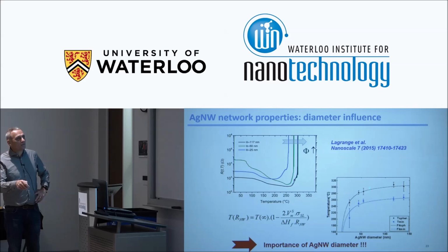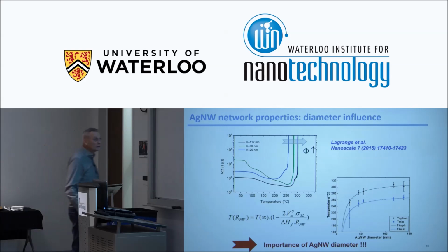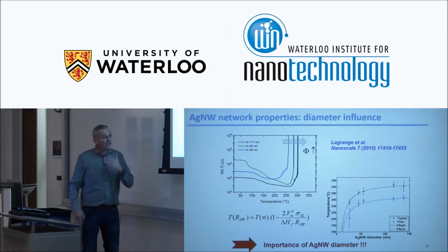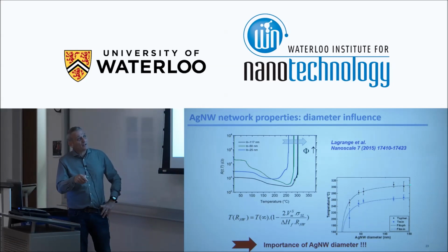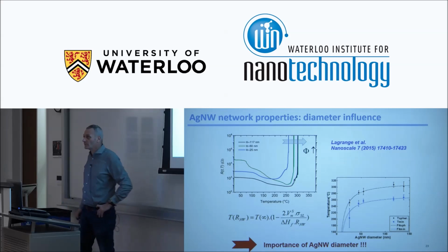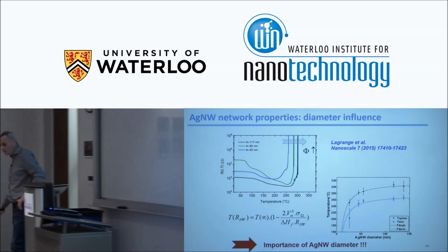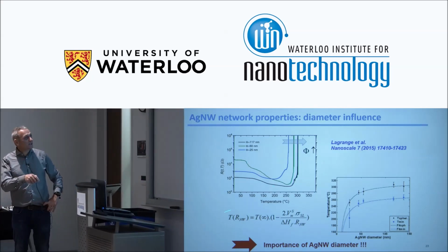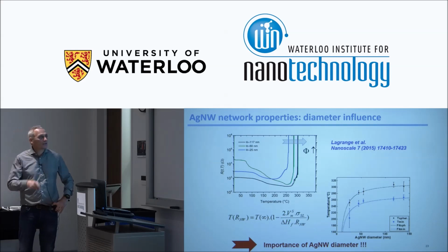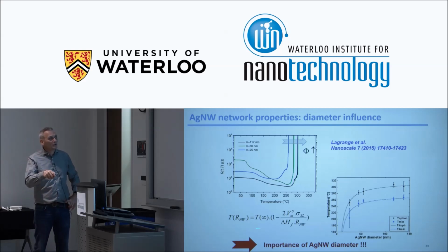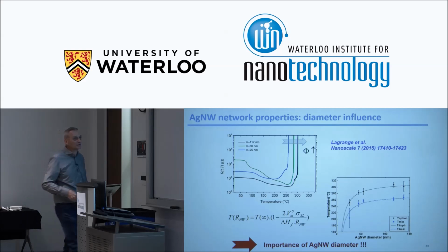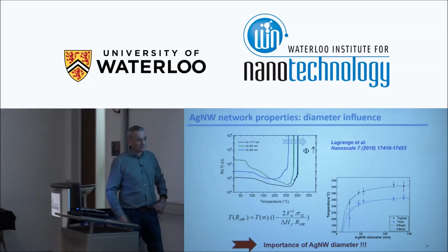These are the symbols, and the error bars correspond to the fact that we have studied a lot of networks with different density, for example, and so we got different results. And if we just use this formula, which comes from the Gibbs-Thomson equation, which is well known in the physics of clusters, for example, they use that often for clusters for plotting the melting point, and it's 1 minus different thermodynamic values, and you have here the radius of the cluster, or here the radius of the nanowire. And it fits pretty well. We have only one fitting parameter, which is this temperature here. So this is the importance of the nanowire diameter.